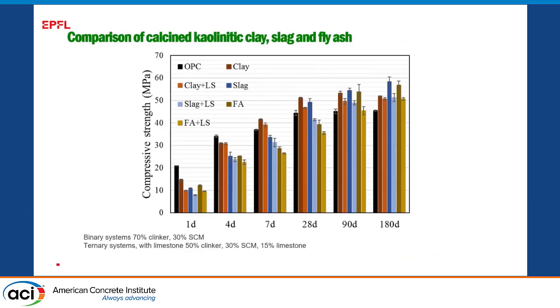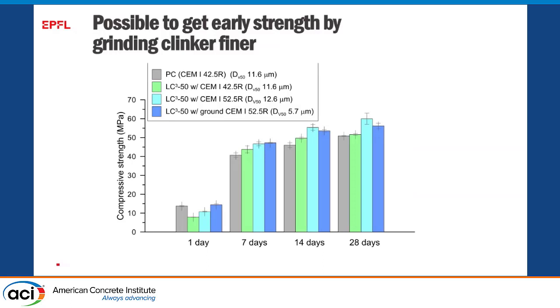And here we can compare the reaction of the calcined clays with slag and fly ash. At long ages, they're all about the same. The issue is that the calcined clays can deliver a lot more early, and from a practical construction point of view, this means you can use higher levels of replacement in practice. And if you work on the grinding a bit, you can even get the same strength at 1 day, as we showed in this experiment here, where we just took a cement, we just reground it, and we could get the same strength at 1 day.